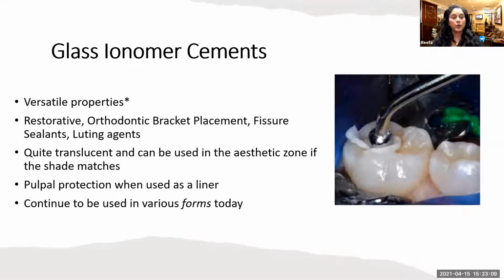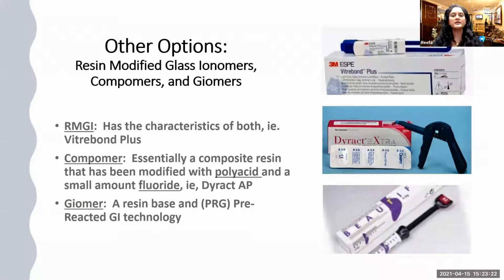It does protect the pulp quite well as a liner, and there continue to be versions of this, just different forms, including restoration material, including glass ionomers. So these are kind of interesting. A resin modified glass ionomer has the characteristics of both. So you're looking pretty much at half composite resin and half glass ionomer. This is amazing. It has all these terrific properties that we talk about. It bonds to the tooth, and there's fluoride release, there's biocompatibility, except now you have a composite in there, so you can polish it up beautifully. It's a little bit stronger. So altogether, a very, very nice material.